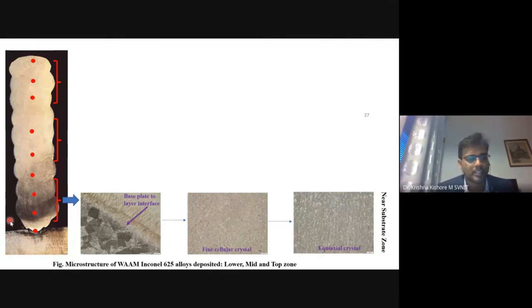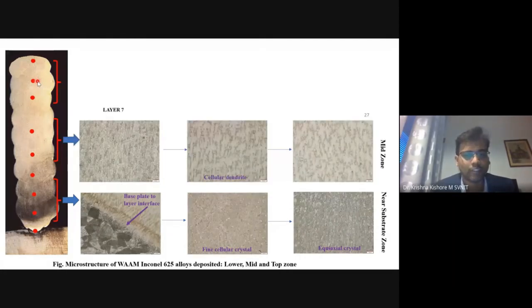So that means in real application, we have to slice off a few layers and then the actual component can be used. Or we can say that some layers will not have similar properties compared with the entire structure, so these layers will generally be machined off. And in the case of the middle, if you see, the cellular dendrites are actually forming because of the continuous deposition of the heat.